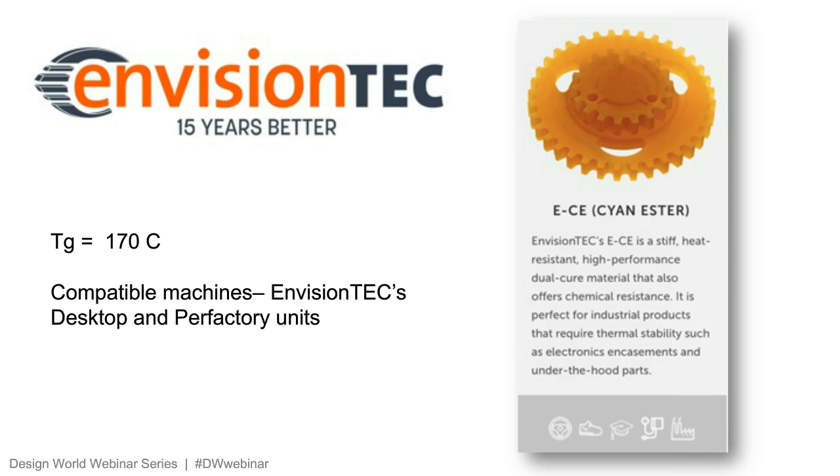EnvisionTEC offers ECE. It's a cyanate ester and is a stiff, heat- and chemical-resistant material. It is comparable to other cyanate-type ester materials in the 3D printing market. It softens at temperatures higher than 170 degrees C, making it suitable for applications that require thermal stability, such as electronic encasements and under-the-hood parts. It is compatible with EnvisionTEC's desktop and Perfactory machines.